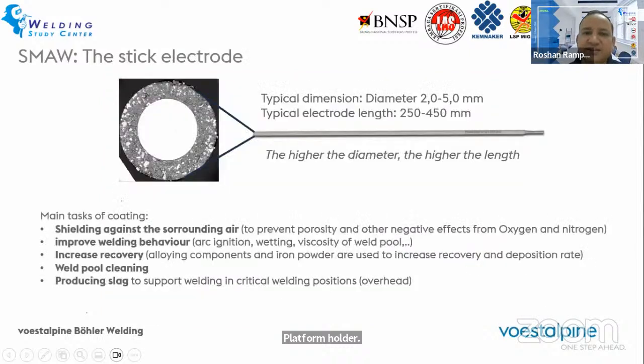The length is measured from the tip to the base of the electrode, and the diameter of the electrode is considered for the diameter of the core wire, not for the total diameter of the electrode, including the shielding. So when you say 5 millimeter electrode, that means this core wire diameter is 5 millimeter, not the whole diameter of the electrode including the flux. This is the diameter of the electrode.